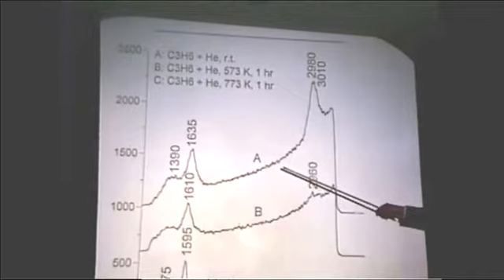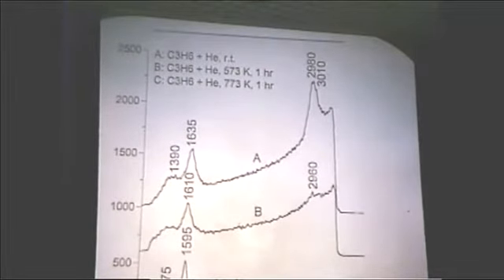All right, so now let's compare this to the USY, which is known to be less resistant to coking. There's a very strong difference in the way the spectra go. First of all, at room temperature, this is just the room temperature propylene adsorption. This spectrum is essentially identical to the ZSM5 spectrum. You can see that the background rises here, so we do get some fluorescence. We don't get away from it entirely, but it doesn't kill us in terms of being able to measure the spectrum. But if I flatten this background out so that it looks like the ZSM5 case, and I lay this spectrum on top of the ZSM5 spectrum, they just lay right on top of each other. The shapes of the bands and everything are identical.